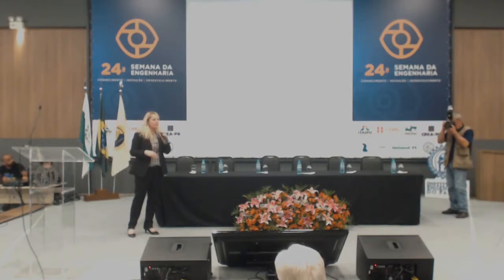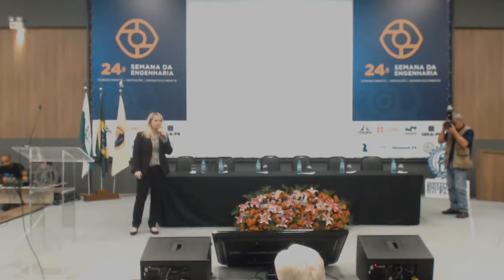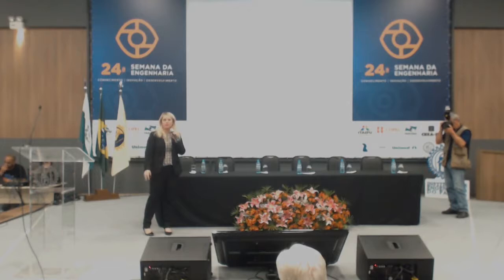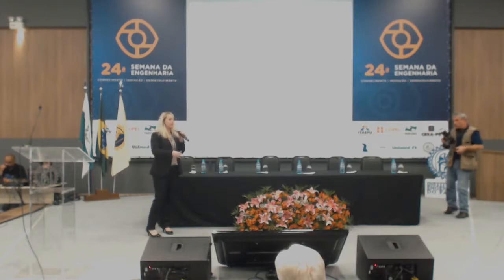Okay. So here is a video demonstrating how these materials work. This bottle on the left is steel wool in water. And as you can see, it starts to rust very quickly. It would start to rust in the time that I'm talking to you tonight. But this is a time lapse done over 2 weeks. And what you notice, the bottle on the right is not rusting over the 2 weeks that it's exposed to the water. And that's because in this water, we added 20 drops of the migrating corrosion inhibitor technology. So the amine-based inhibitor was added into this test bottle.